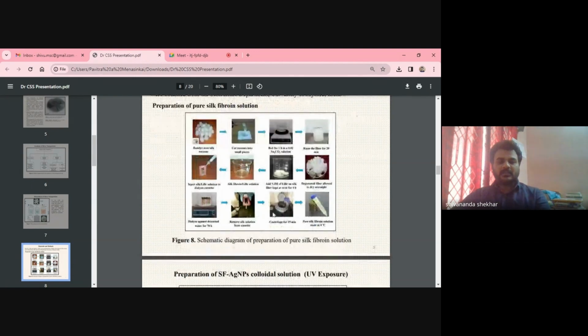Here, we cut the silk cocoons into small pieces. Then we put them into 1 liter of hot water and heat the beaker for 1 hour. Later, the sericin coated over the fibroin is removed, because this is the gumming material. After 1 hour, we take the fiber, squeeze it, and dry it for 2 days. Later, the dried fiber is put in a beaker and 9.3 molar lithium bromide is added to the dried fiber. Then we get the silk fibroin lithium bromide solution, as in this figure.